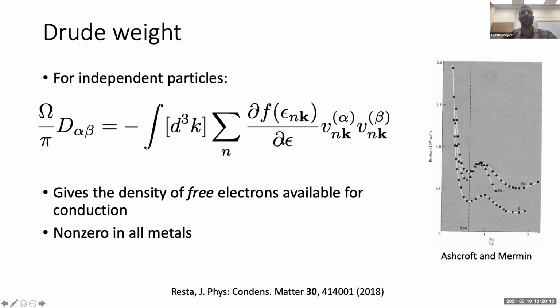There are a lot of ways of writing down the Drude weight, and there is a very nice review of the physics of Drude weight that I would recommend here. In this way, we've written it down as a Fermi surface integral. We have here a derivative of the Fermi function, so it's only sensitive around the Fermi surface. And then we have some band velocities in different directions. The Drude weight basically gives the density of free electrons available for conduction, and as a result, it's non-zero in all metals. In fact, you can consider it as a definition of a metal to have a non-zero Drude weight, and a definition of an insulator for the Drude weight to vanish. Since it's non-zero in all metals, no matter what metal we look at, we get this peak in the optical conductivity as we go to low frequency, which is in chapter 1 or chapter 2 of Ashcroft and Mermin.